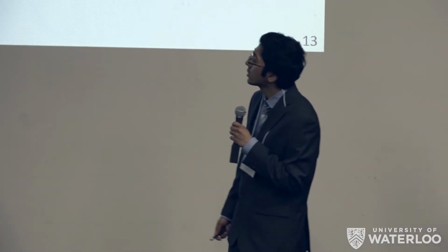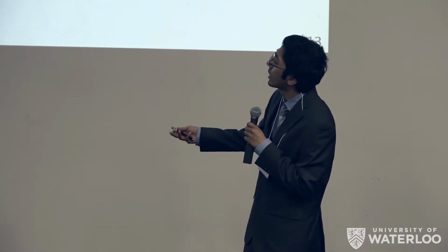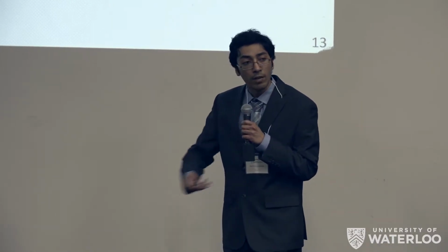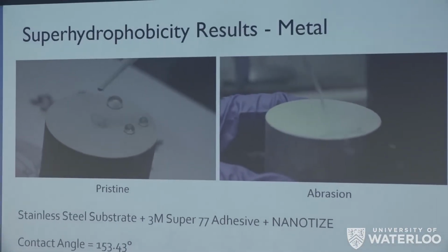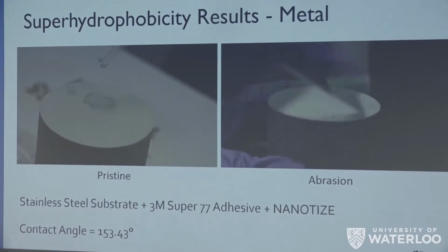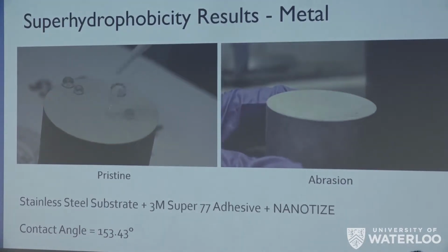We had similar results coating metal as well. Once again, the surface is superhydrophobic after a simple spray treatment of our coating. And again, if you watch on the right-hand side, it's able to withstand the scratch test, remain non-wetting, and again, durable for months after.